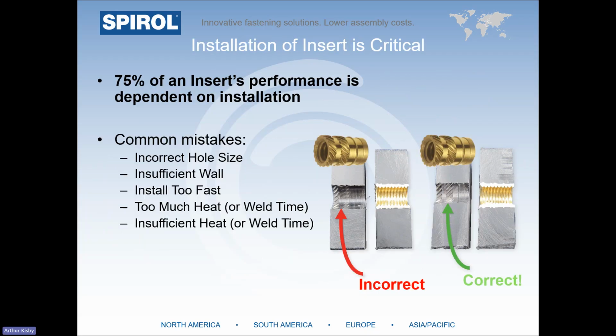There are many factors besides an insert's design that affect how it will perform in the assembly. As the quality of the interface between the insert and the plastic component is so critical to how much the insert can withstand torsional and axial loading, the quality of the insert's installation is paramount. These images demonstrate how SPIROL recommends validating the installation quality through a destructive test. We recommend cross-sectioning the plastic after the insert gets installed so that this interface is clearly visible.